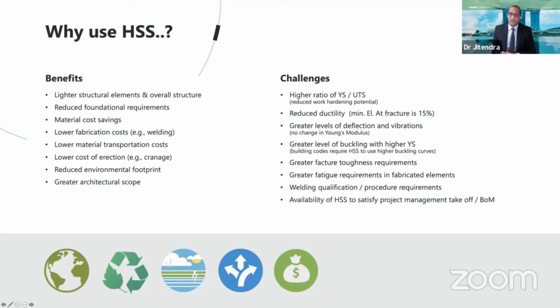As we know, if you go to higher strength steels, the yield to tensile ratio starts to narrow. We start to approach one because of the types of microstructures we depend on to get these higher strengths, and therefore the reduced work hardening potential comes into play. We know that the elongation on these steels also starts to decrease. But at the 460 level, there's not too much effect or impact. So we can go from 355 to 420 to 460 without really making too much of a difference in the performance behavior of these steels, and coming to the stricter restrictions of yield to tensile ratios or fracture requirements.